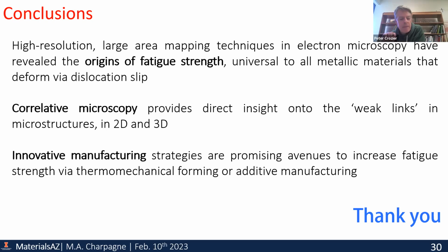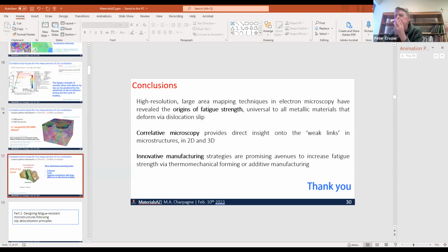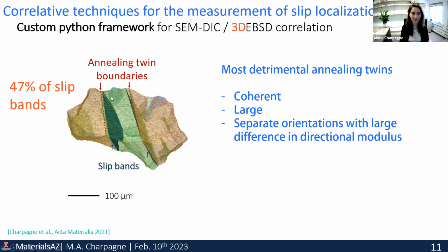The other, just a follow-up question then, and I apologize if you already said this, I had a slight interruption. So the slip planes, I wasn't exactly clear on the relationship between the slip planes and the twin boundaries. You say that the slip planes are close to the twin boundaries. Yeah, for sure. I went really fast with this because I look at this all the time, but that's a very fair question. So this is your twin boundary plane right here, and it's inclined. Crystallographically, this is the same 111 plane type as where the slip band develops. Am I reading the image correctly? The slip plane is about 100 nanometers away from the twin boundary plane, is that correct? Yeah, absolutely. So that's what I wanted to find out next.